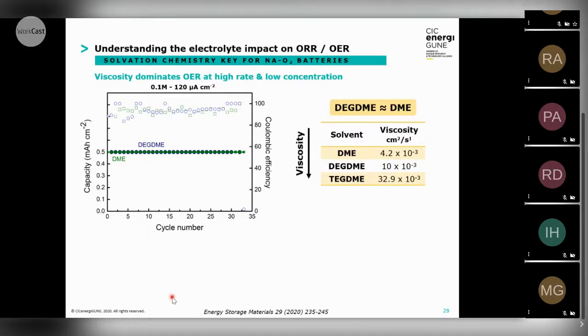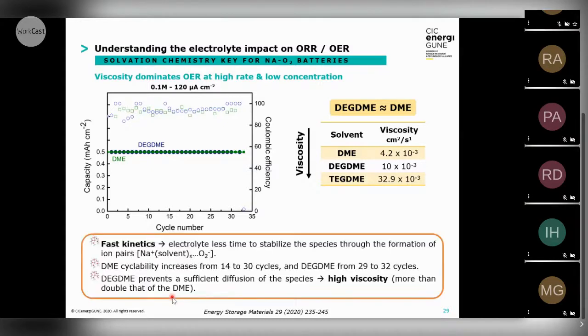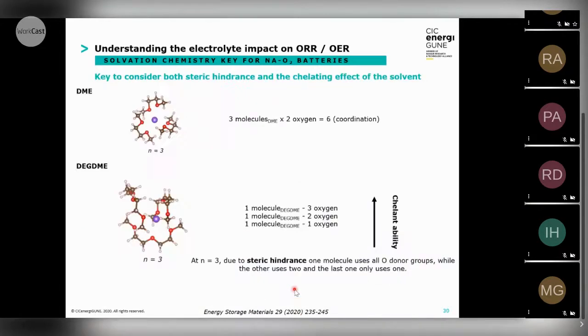If we look at the viscosity, the diglyme viscosity in this case is higher, and here the electrolyte has less time to stabilize in the solution and form these ion pairs of the sodium solvent with the superoxides. And that might be the reason why the higher rate or this solvation is less important, because we can see that the performance is quite similar.